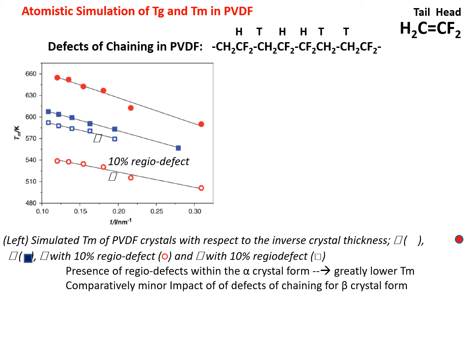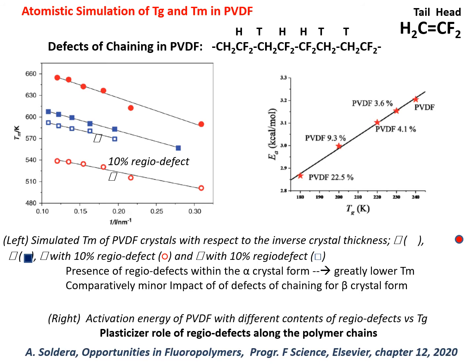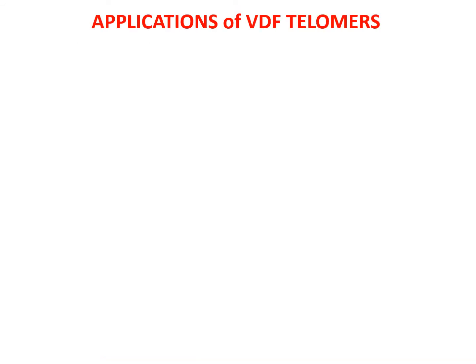On the other hand, he measured the activation energy of PVDF versus the Tg, and showed that the higher the ratio of defects in PVDF, the lower the activation energy, and also the lower the Tg. So this shows that probably the presence of defects plays a plasticizer role in the PVDF.